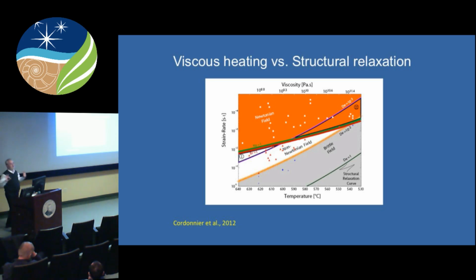viscous heating effect. So that at the very interesting temperature of about 600 degrees Celsius, which really is relevant to dome lavas, you can go from a regime where you will hit first the viscous heating effect, and the viscous heating effect will have the effect of pushing you back away from the glass transition, because you've dropped the viscosity. You're more liquid than before, not less. Whereas if you don't do it in that regime, you will hit the blue line first, which is the onset of structural non-Newtonian viscosity, and you will never get to the viscous heating, it will break first.